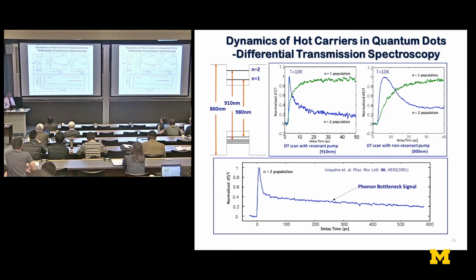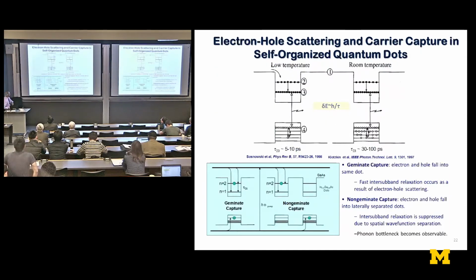So he sorted all that out, and he figured out that the fast transient is due to what he called geminate capture, when the electron and hole are in the same dot, and the slow transient is due to non-geminate capture, when the electron and hole are in different dots, or the holes are not there. And that's what that is about. And the fast transition from the excited state to the ground state happens in quantum dots, not by phonon scattering or anything, but by an Auger-like mechanism, but it's a 2-carrier mechanism, which we called electron-hole scattering.